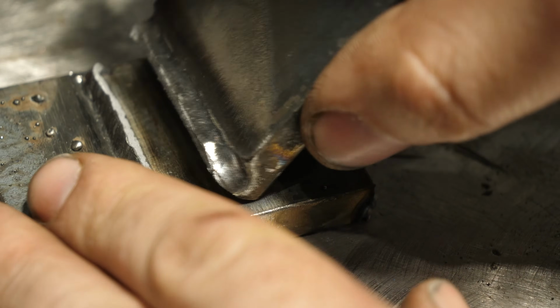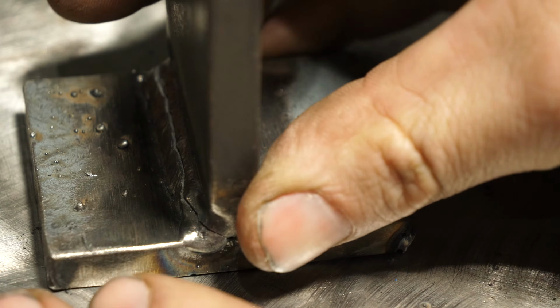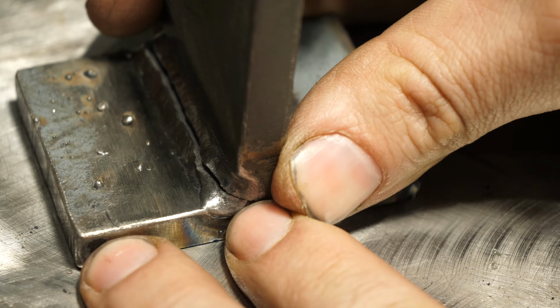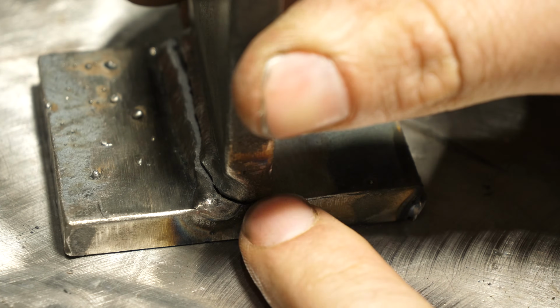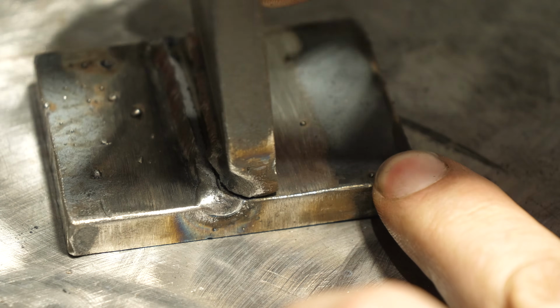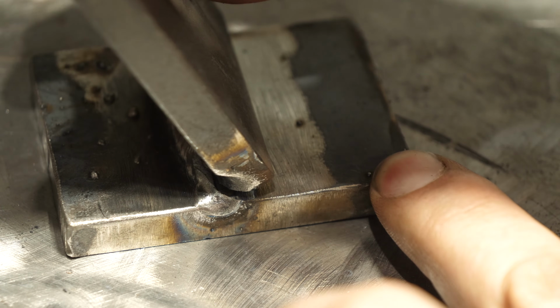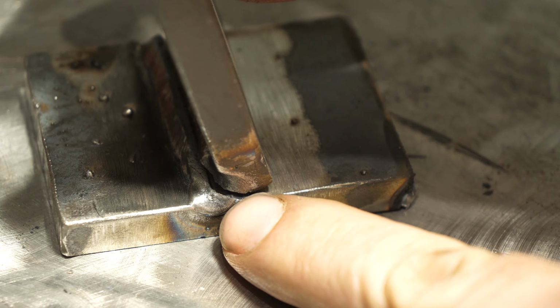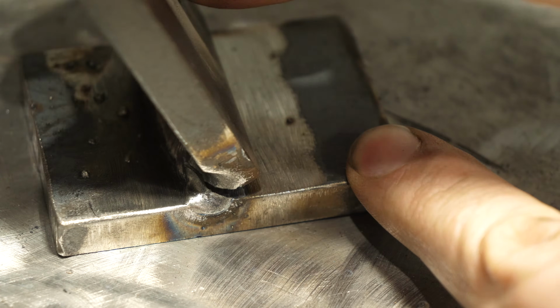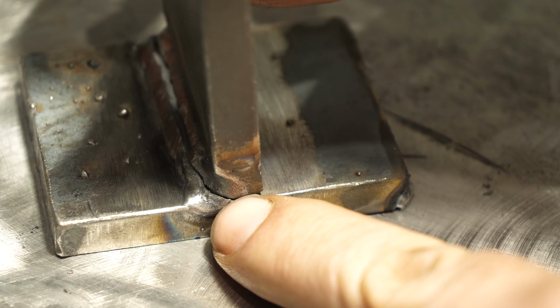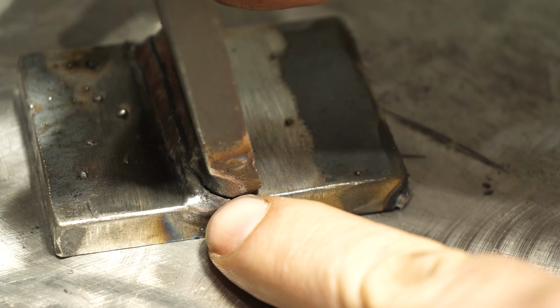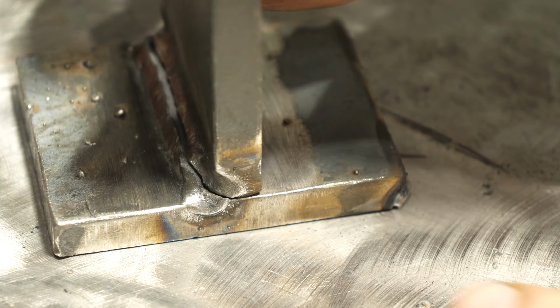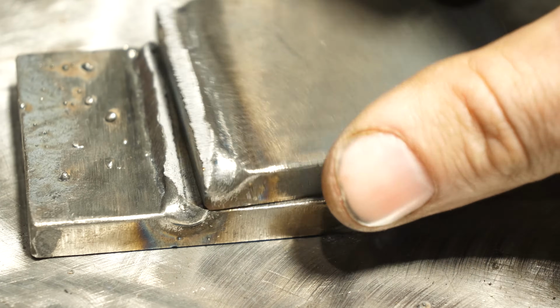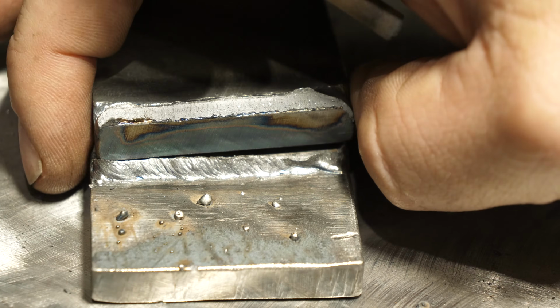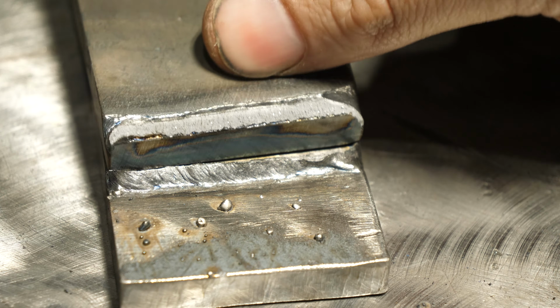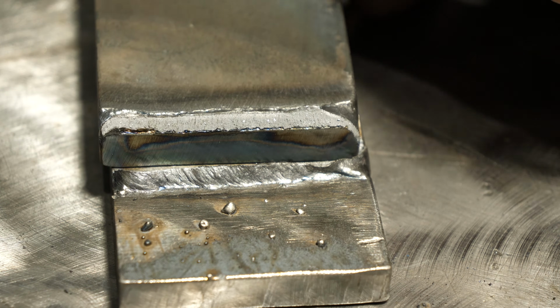And the issue with not having root fusion is that on a single weld like this, with no root fusion, what ends up happening is the weld, when you stress the weld towards the face, the plate can lift up off. And the further in the penetration is, the more you end up having to tear the weld that's internally there, and it takes a lot more force. And that's why like 6010, 6011, even short circuit MIG in this test did better than this particular rod.